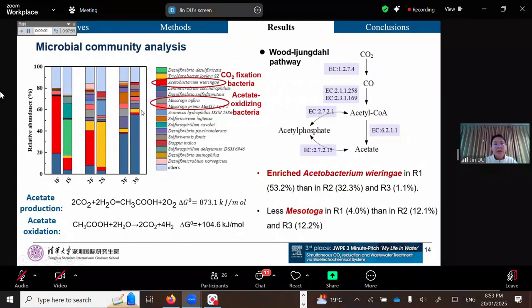Subsequently, we sampled the biofilm and the suspended microorganisms from the cathode chambers of the 3 reactors. The results explain the reactor performance in the previous section. First, Acetobacterium, the key CO2-fixing bacteria, is more enriched in R1, far exceeding the levels in R2 and R3. Second, R1 exhibited lower levels of Mesotoga, an acetate-oxidizing bacteria, likely because the higher CO2 partial pressure inhibited acetate oxidation from the thermodynamic aspect.